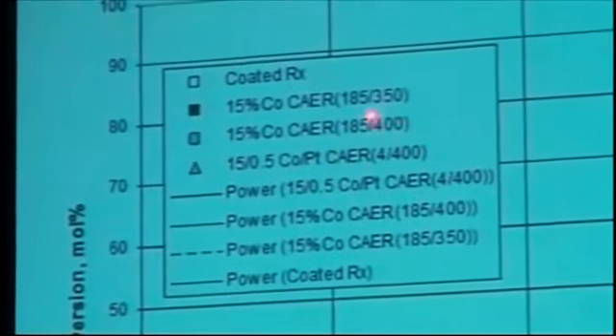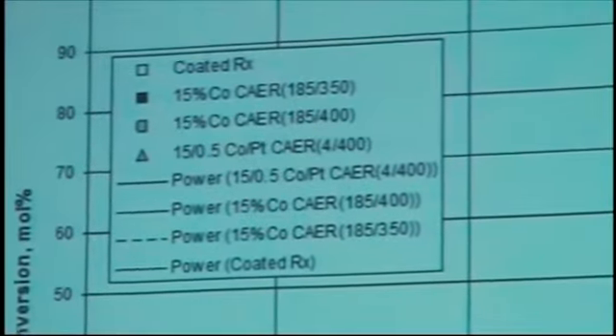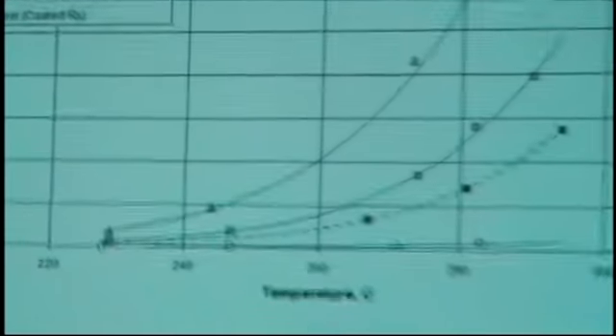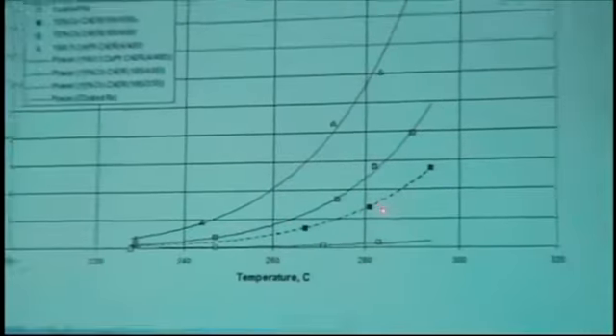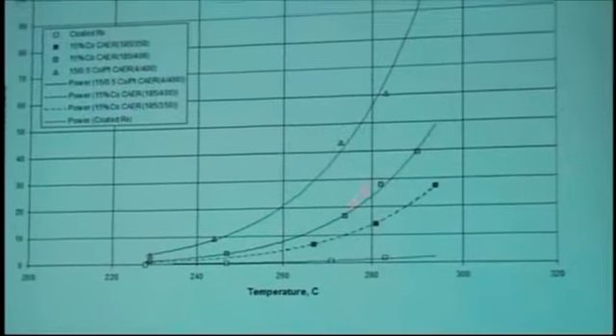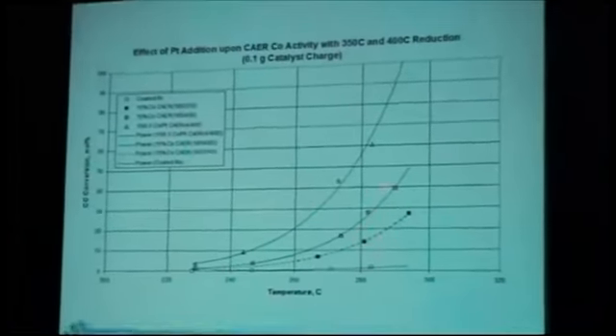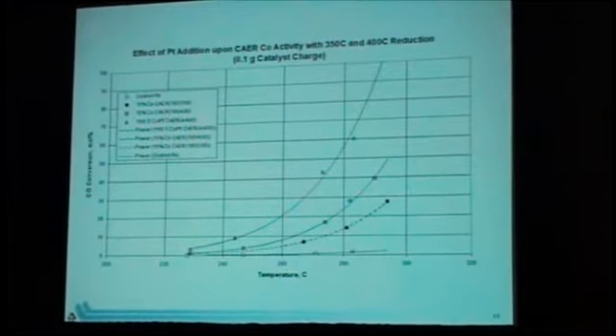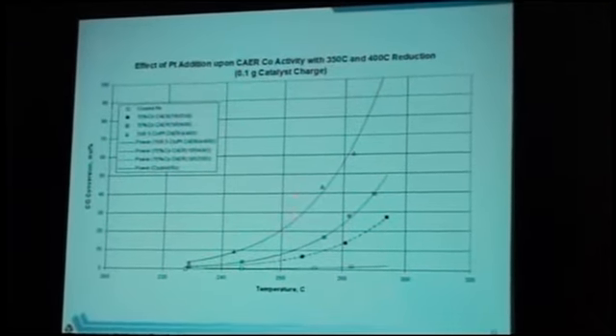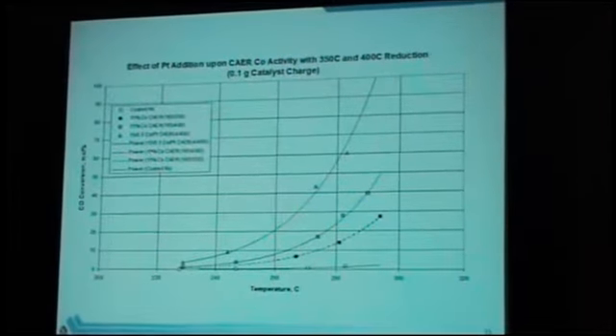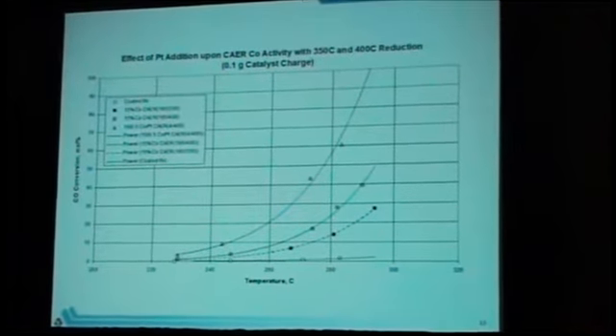In looking at 0.1 gram of catalyst charge, the 15% at 350, well, again, the reactor itself, 350, 400, we're talking about that significant change. And going up to the CAER, the incipient wetness catalyst was much more effective.